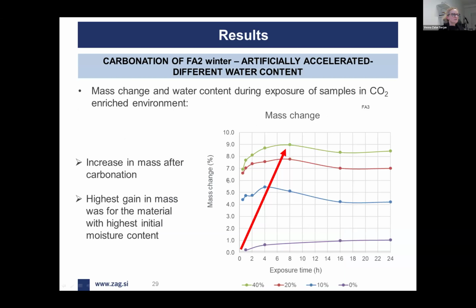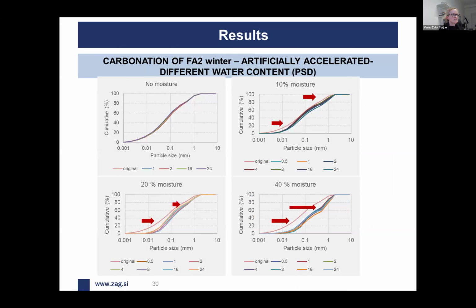It was very obvious that an increase in mass happened after the carbonation, and this increase was the highest for the sample in which the quantity of water was the highest. So the 40% of water added to the material was reflected in the higher increase in mass. The particle size distribution also showed that the more water was added, the distribution moved to the right, which means the carbonated ash particles were larger in comparison to only 10% or 20% of moisture added. And of course, the larger grains were measured at larger time intervals.